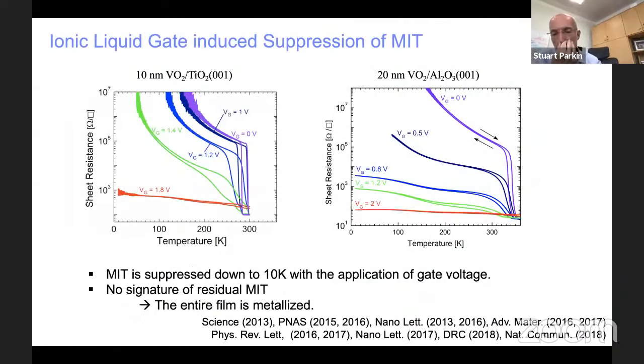and the oxide. And this we demonstrated a few years ago in a paper in Science that we could, for example, in the case of vanadium dioxide, shown on the left, you can see the resistance versus temperature, and just close to room temperature, the resistance of the metallic material above that temperature switches to an insulating material shown by the purple curve. And what we demonstrated was by applying, using an ionic liquid, a large electric field, we could completely suppress this metal to insulator transition, and you develop the red curve you can see, in which the resistance only weakly changes with temperature.